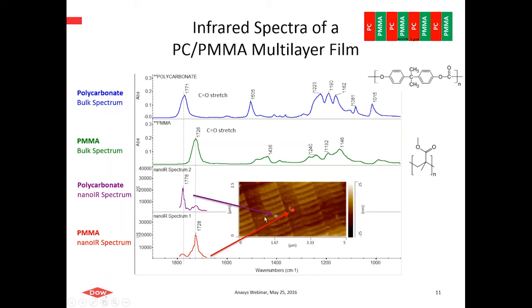And in the middle here we have a polished cross-section of the surface of this co-extruded layer. This is just an AFM height image. If you see my cursor, the vertical bands are alternating layers of the two polymers. The horizontal stuff is just a little bit of chatter due to the prep in the sample. So now we look at the infrared spectra of the two components. This is bulk IR spectra of polycarbonate at the top, PMMA below. And we see in the carbonyl stretch region for each of these polymers, we've got very good spectral resolution. That is, there's about a 50 wave number separation between the carbonyl stretch in these two polymers.